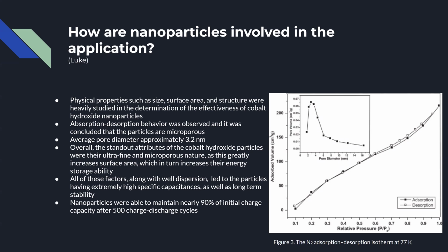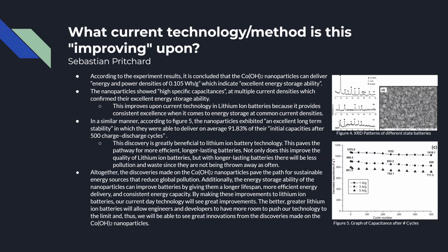So overall, the standout attributes of the cobalt hydroxide particles are the ultrafine and microporous nature, as this greatly increases surface area, which in turn increases their energy storage ability. All these factors, along with well dispersion, led to the particles having extremely high specific capacitances, as well as long-term stability. And an example of that stability is that the nanoparticles were able to maintain nearly 90% of their initial charge capacity after 500 charge-discharge cycles.